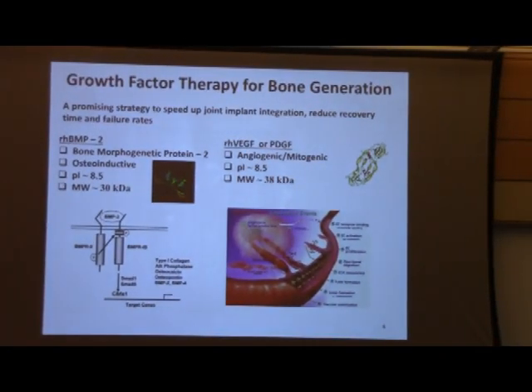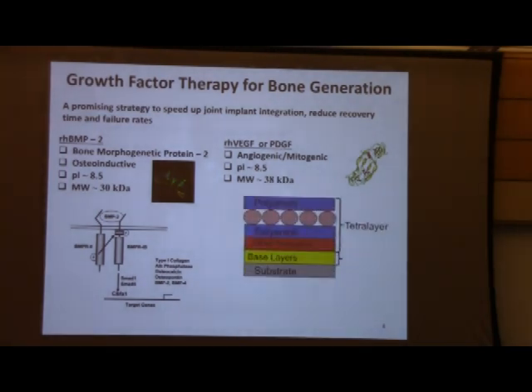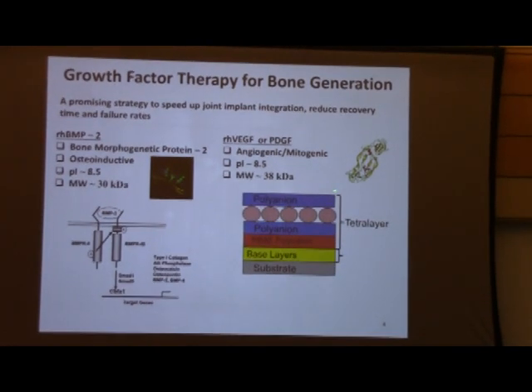Now, these are proteins that have very real therapeutic value, but to us, in the end, they're just really complicated looking polymers. And we will look at a protein like this, understand what its isoelectric point is, the point at which it undergoes a switch from positive to negative, and then, based on that, we'll know whether we can treat it like a positively charged polymer or a negatively charged polymer when we introduce it into our layer-by-layer films. These growth factors happen to be positively charged at pH 7, and so we treat them like a positively charged material in a layer-by-layer film.